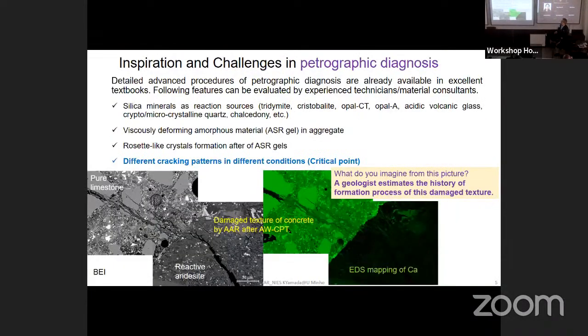Then think about this again. Crack forms here, from here, to penetrate into other aggregate. But after some time, this crack in cement paste is exchanged with calcium, and this crack must be choked or closed with this chemical reaction. So in this crack, alkali gel can be restored again. But if the generation of alkali gel is fast enough, it will be difficult to close this crack by chemical reaction.